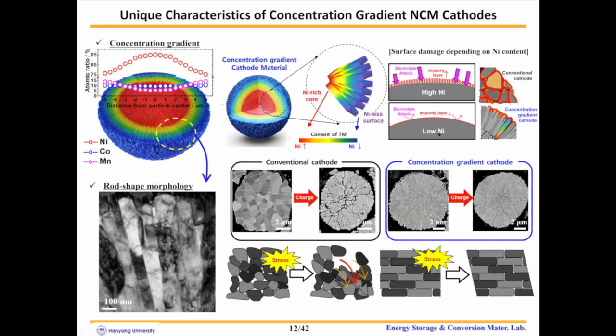as you can see here. And the secondary concentration gradient cathode consists of long, large shaped primary particles, whereas the conventional cathode is composed of large equiaxial polygonal shaped primary particles. As you can see in the cross-sectional SEM image, the conventional cathode material easily developed significant microcracks induced by the internal stress during the charge. However, the larger shaped primary particles of a concentration gradient can effectively dissipate internal stress and thus minimize microcrack formation within the cathode particles.